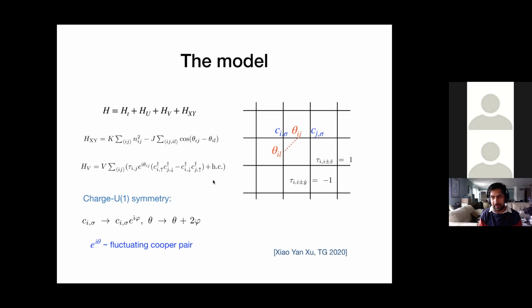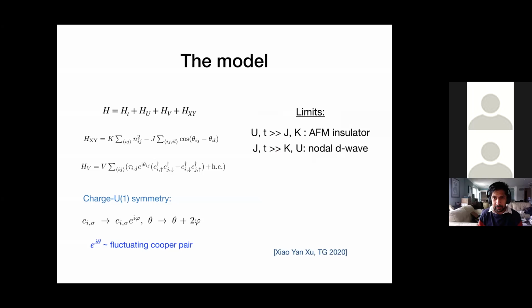That's the main observation. At least we have been looking for such models for some time, and we did not think it would be easy or possible to find a nodal superconductor. I have not seen other models which I can argue don't have sign problem and show that it has D wave. So that was the excitement, and that's why we worked on this. In various limits, you can argue it has antiferromagnetic insulator and also some nodal D wave. That I leave as an exercise.